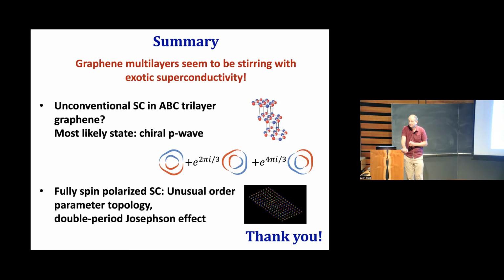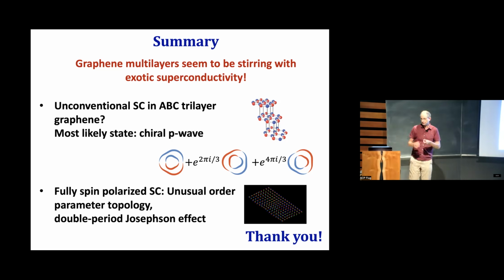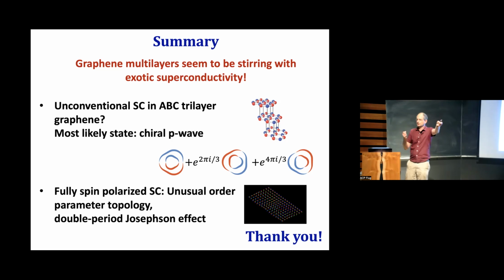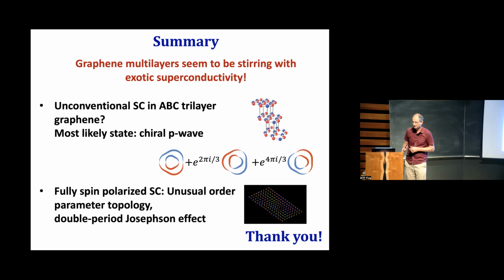Andrey, do you know in theory why one phase is spin triplet and another spin singlet? Right. So in terms of the strongest interactions in the problem, which are the Coulomb interactions, which are maximum at small q, the two phases should be exactly degenerate. So their balance is always subtle. And it turns out that if you just run this mechanism and include the large momentum transfer scattering, which is much weaker, that actually chooses singlet for SC1. Now, in SC2, the normal state is a ferromagnet. It has to be spin triplet.